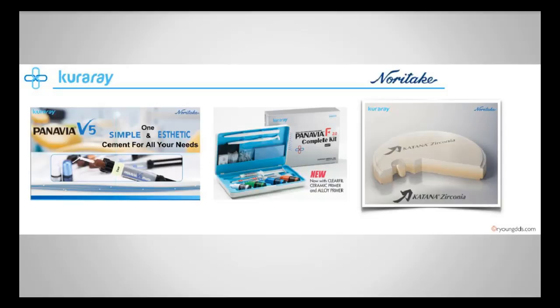We're also going to talk about Katana zirconia. It's a gradiated puck, so your labs can position the restoration in here and get a much more lifelike restoration. In strength, it's kind of halfway between e.max and pure zirconia. And so look into this product. It's a really, really neat product and really wonderful to work with in the posterior region. And they're doing anteriors. It comes in ultra translucent, super translucent. So the ultra translucent, the UT, they're even milling veneers out of this product. It's pretty amazing with the labs.